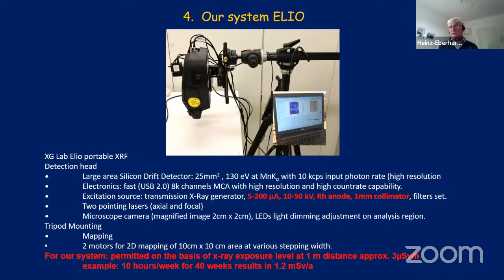The total power consumption is in the order of a few watts in the X-ray beam, and that means typically about 100 watts or maybe up to 500 watts is needed to power the system, which is then possible for field studies with battery stacks, with power packs, to be operational in field research. The system shown here is the so-called ELIO system, which was originally produced by an Italian company. Now it's taken over by Bruker. It has the nice feature that the X-ray beam is focused down to a 1 millimeter spot size. All the other available handheld, easily operational X-ray fluorescence pistols, so to speak, typically have something like a 6, 8 or 10 millimeter beam spot.